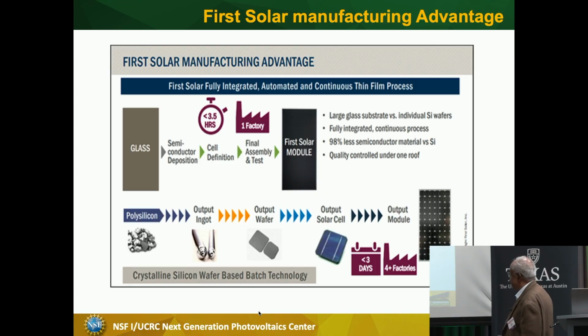Now, once you have polysilicon, you make an ingot. You melt it down and slowly cool it, and it takes days. You can't cool it fast. There is a problem. And then you get a wafer. You have to slice it into slices, and then you have to clean the defects that you have created on the surface. And then you make a solar cell, which has many, many steps. It's not a completely inline, automated line for all that it takes to make a solar cell. And then it takes some more effort to make an output module.